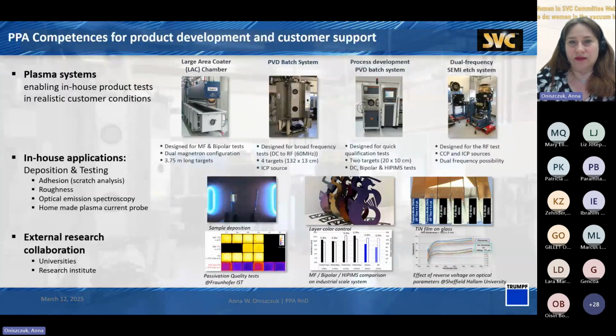And from in-house tests, we have different chambers in the plasma group, where we can do different kinds of tests. We can do plasma tests in the chambers, like a small chamber for a batch system. Also, we deposit samples here, and then we can test the samples. However, most of the investigation we do with the plasma, with optical emission spectroscopy and with a homemade plasma current probe, because this gives us a very fast indication if we are going in the right direction with this process, if we increase the energy, if we increase the quality of the plasma. Then we can deposit some coatings and do some simple tests, or do cooperation and send samples for investigation.